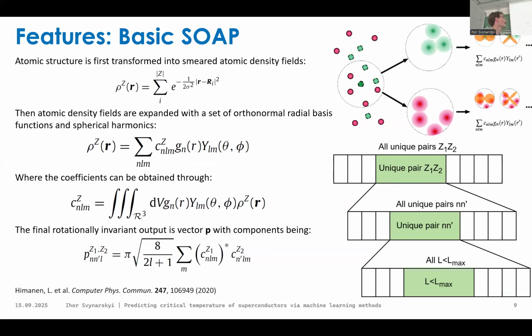So we calculate this descriptor for the particular atomic site, and then calculate it for each site in the unit cell, and then just average them. That's how you construct, let's say, the average description of atomic environments in the unit cell. You just take it for every single site and then average over the cell. But this method only works for stoichiometric compounds with pretty good numbers of species in the formula. And we know that for superconductors, there is a pretty high probability that our formula would have some ugly, non-stoichiometric numbers.